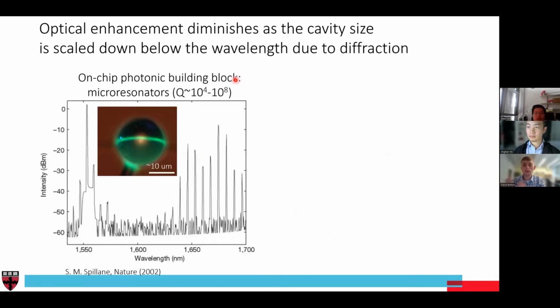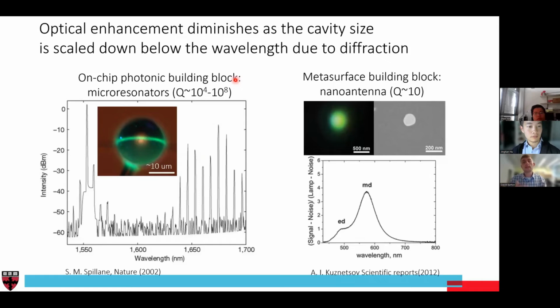And the big challenge is that these structures that I was showing earlier are actually quite large, on the order of microns, tens of microns, or even larger. What that means is that you can't design these nano antennas, which have to be very, very small. In fact, when you scale these down, like I showed you in the plot earlier, typical nano antennas are quite small, but their quality factors are necessarily very low by design. So finding ways to engineer and combine functionality from these micro resonators and nano antennas would be quite powerful.